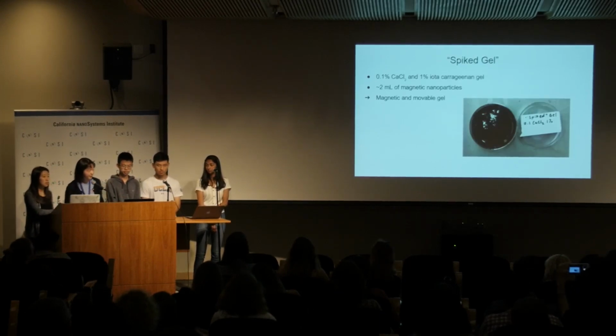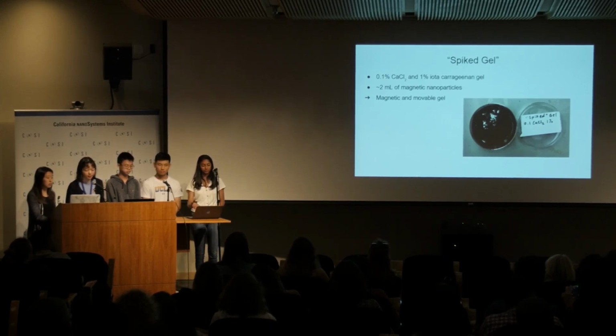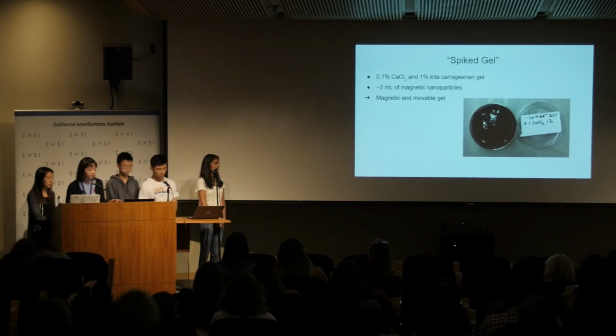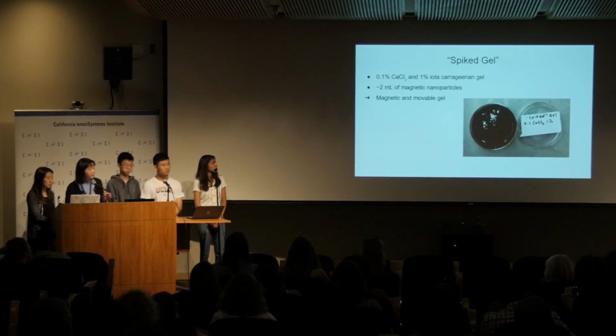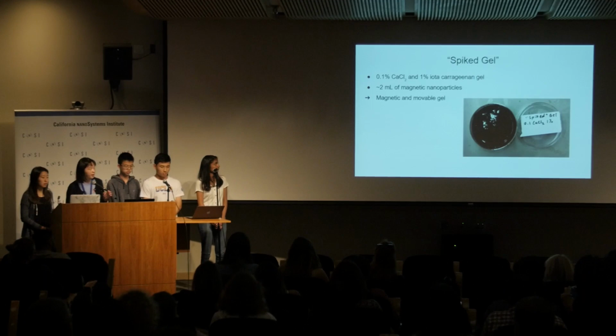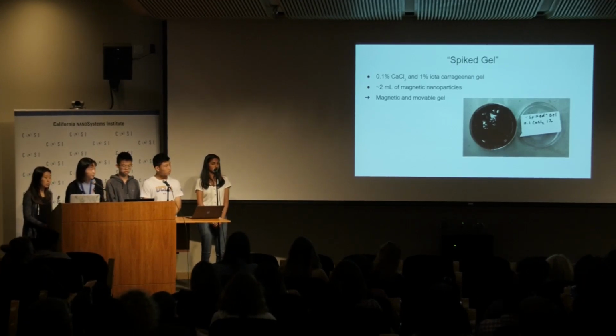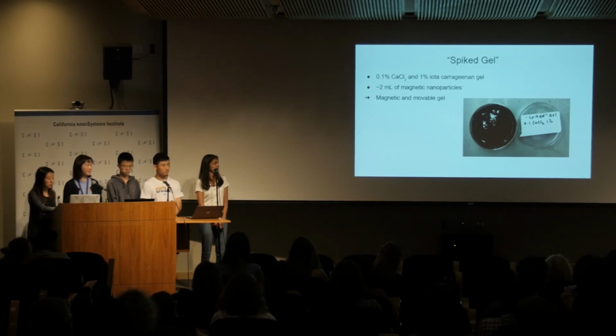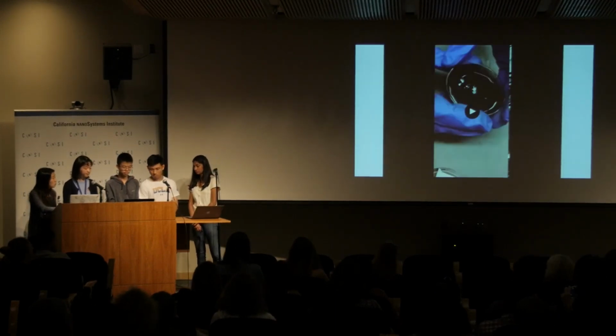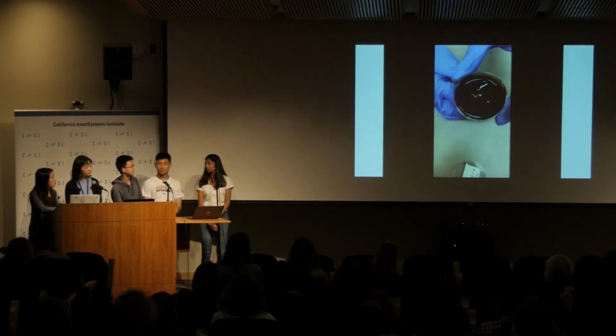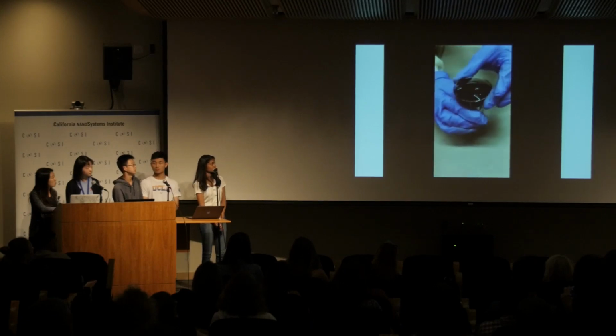So at this point, we hadn't really gotten a magnetic gel, so we decided to take one gel that was not too stiff but not too liquidy, and spike it with a whole bunch of ferrofluid. In our 0.1% CaCl2 and 1% iota-carrageenan gel, we added around 2 milliliters of magnetic nanoparticles, and that made the gel extremely magnetic and movable. As you see, it responds to the magnetic field, like we hoped.